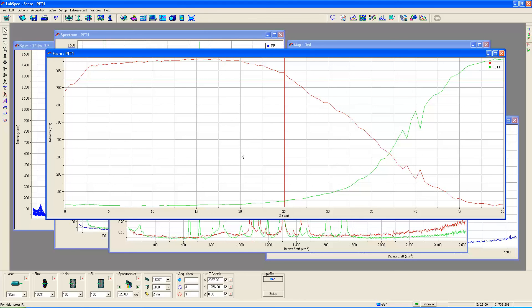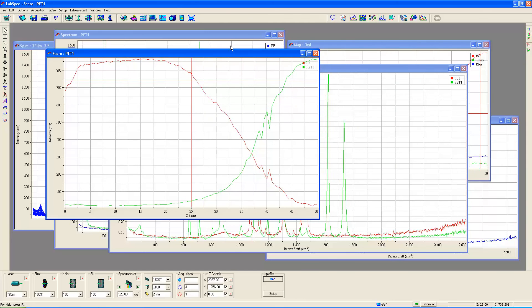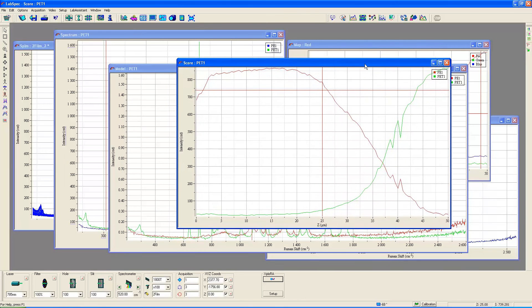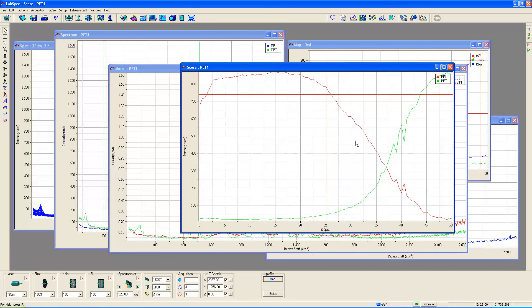Now what you can see is that in my depth profile that's generated from the modeling, now we have a depth profile that is not just from one peak but from a depth profile generated from known reference spectra. Here we see now a much sharper interface than we saw with the one peak.